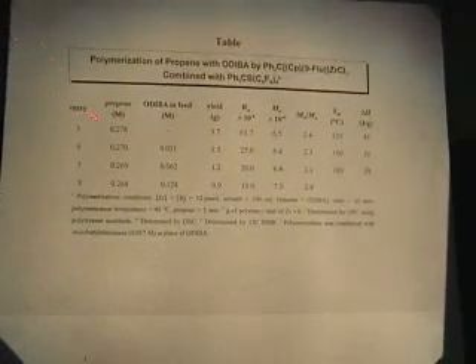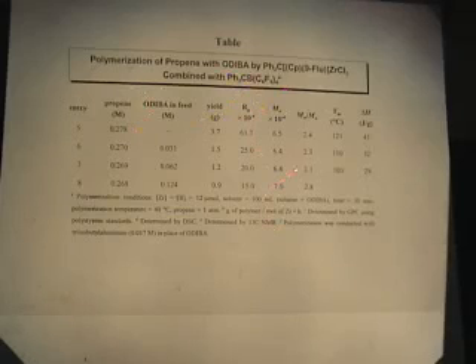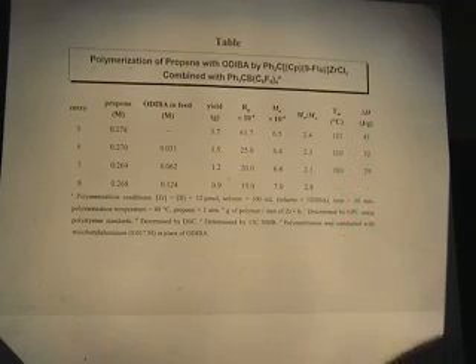Additionally, this is the polymerization of propylene by the syndiospecific metallocene catalyst combined with the same anionic complex. Activity also decreased with the addition of aluminum, but the rate of decrease is less than that for the isospecific catalyst. The number average molecular weight did not change much. It means that in the case of syndiospecific polymerization, chain transfer to aluminum did not occur. The thermal properties show the same tendency as the isospecific polymerization.